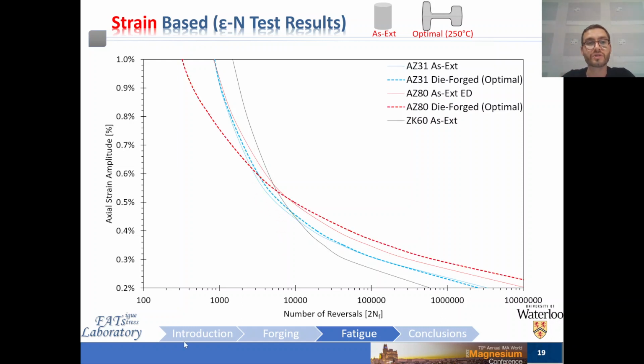Now the effect due to forging of AZ80 is more complex, as there is an appreciable increase in both strength and ductility once forged. This dramatic increase in yield strength manifests itself as higher cyclic stresses in the low cycle regime under strain control fatigue testing. This results in a large amount of cyclic damage and strain energy density per cycle, and a lower eventual life. So this is that red region here.